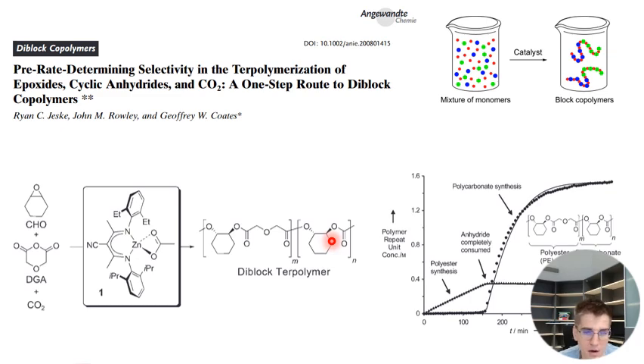So usually how you would make block polymers is like in living polymerizations. So in one where the chains grow regularly, so to say, and initiation is fast with respect to propagation, you'd first just have a mixture of these two, let them polymerize, and then only once this is consumed, you'd add the CO2. Yeah, so you'd only pressure it with CO2 once the anhydride is consumed. That would be a traditional way to make a block copolymer, but the Coates group, like 15 years ago or so on, well, you can also just mix those three, and by pre-rate determining selectivity, you form this block polymer.